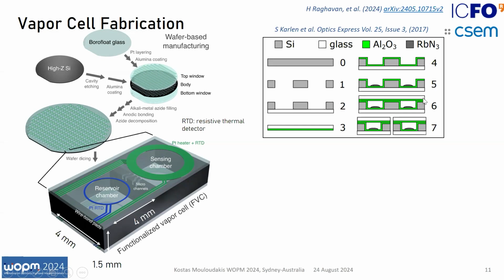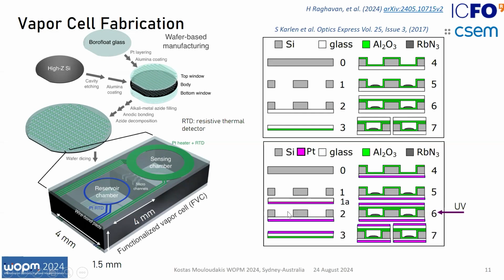The top glass is anodically bonded, and then the wafer is etched. In our case, we have an extra step in this sequence where these heater traces are lithographically deposited in the glass. After the vapor cells are filled, we use UV radiation on the whole wafer, and we irradiate for hours such that the rubidium azide is decomposed into rubidium-87 and nitrogen buffer gas. And in this case, we can achieve very high buffer gas pressures.